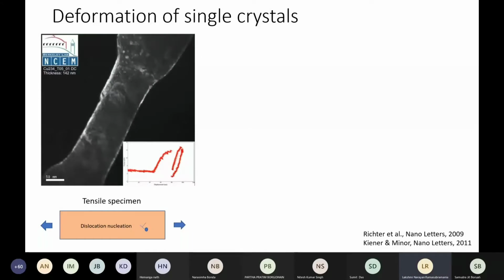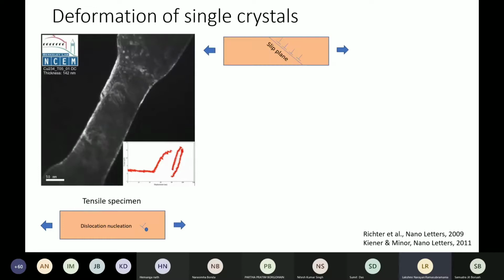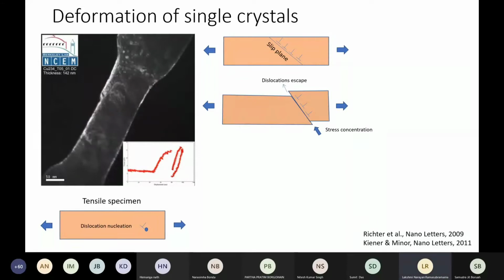First, when you have a tensile specimen of a single crystal, you do not have a lot of defects at the submicron level because your defects are going to be statistically less in a material which is so small. So your material has to nucleate dislocations, and that is why the strength is also high. When a dislocation is nucleated from a source, it will start moving on a particular slip plane. And as it keeps moving, the dislocation will see the surface and escape. As we had seen in the previous figure in the first few slides, the dislocation moves from one end to the other. When it escapes, it creates a surface offset.